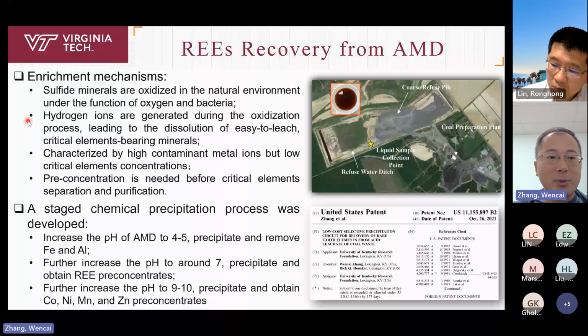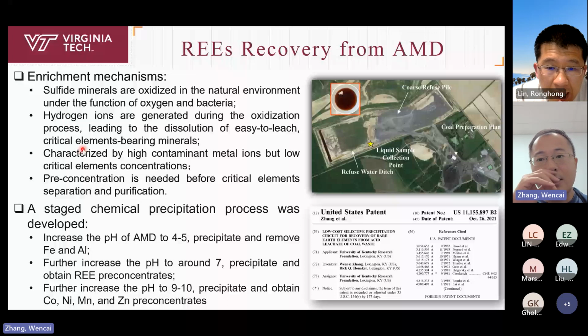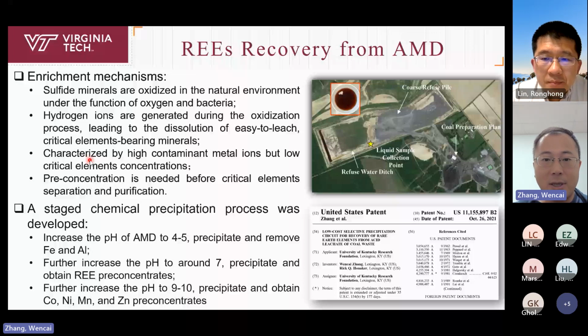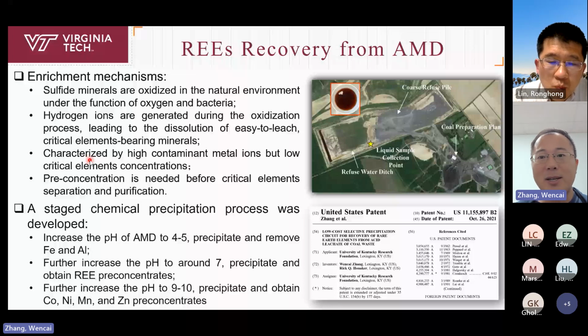And what we did is that we developed a process that can pre-concentrate the rare earths from the acid mine drainage. We call this staged chemical precipitation. So the concept is very simple. Different metal ions in acid mine drainage have a different precipitation pH range. If you can choose the pH range and collect the precipitate formed in the range where the rare earths are precipitated, then you can get a pre-concentrate of the rare earth elements.